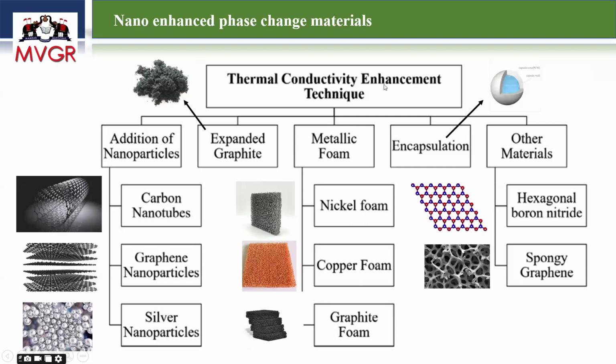Another technique is encapsulation. In this encapsulation technique, as I already told, the core material is PCM only, but the outside shell may be of some organic material, sometimes silica based material, titanium based material, or some kind of metal materials. So the PCM is completely enclosed with the shell material.